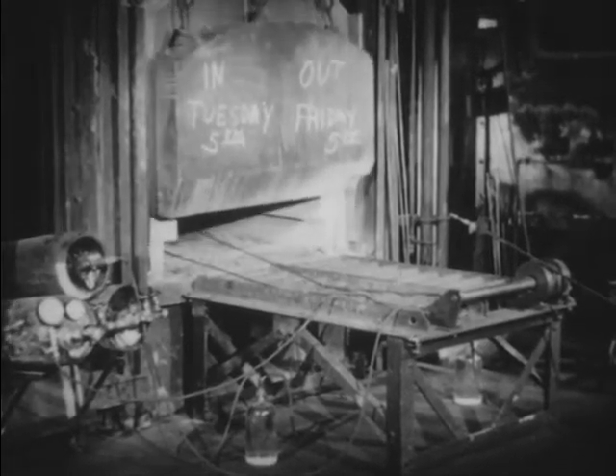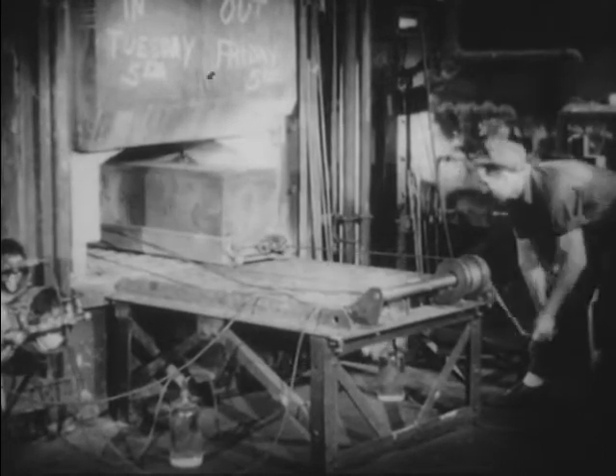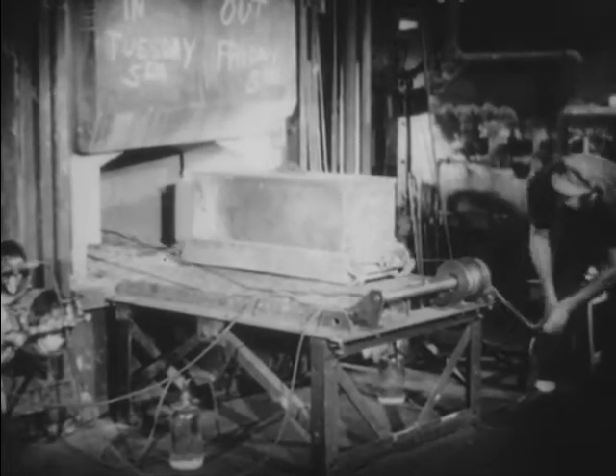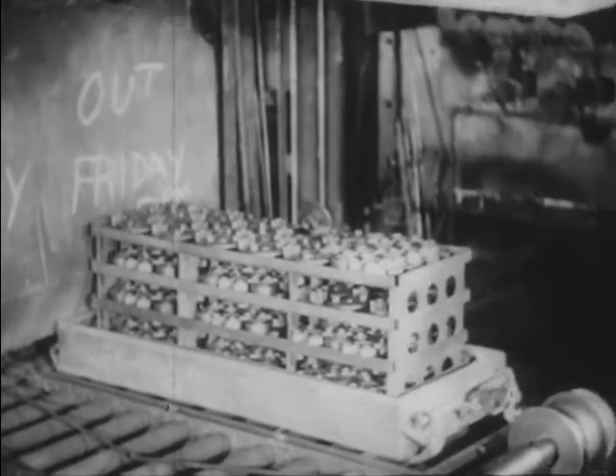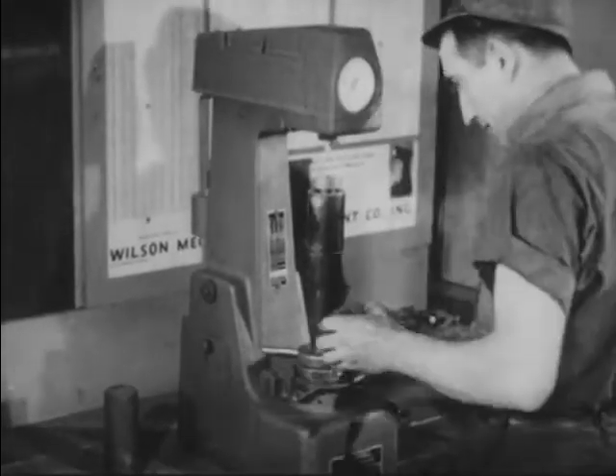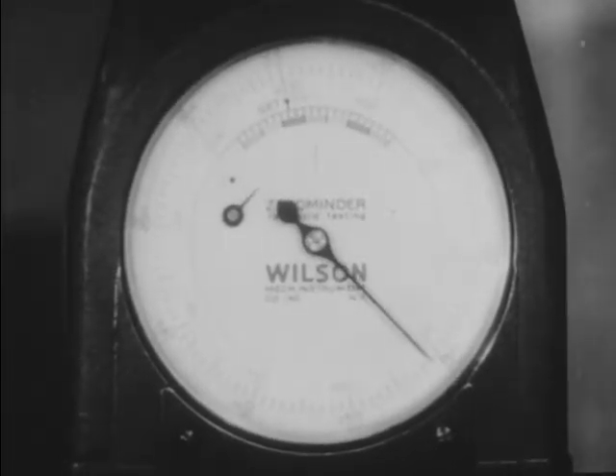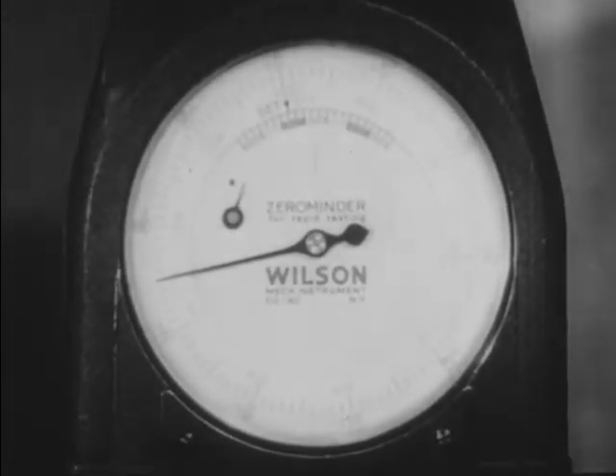In this case, the parts which were put in the furnace Tuesday at 5 p.m. are taken out on Friday at the same time. Under heat, the ammonia gas circulating over the parts has decomposed, forming nitrogen and hydrogen. The nitrogen has combined with some of the elements of the steel to form a very hard nitrided case. Since the nitriding temperatures are low, distortion of these precision parts is negligible. Nitriding can achieve hardnesses exceeding those obtainable by any other known treatment of steel. Through this treatment, parts attain a hardness range of 72 to 80 on the Rockwell tester. The highest hardness obtained by other methods is about 68.